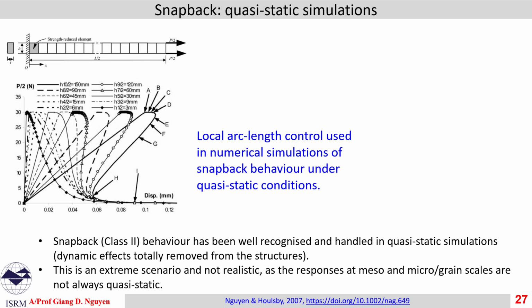So the first thing is this snapback. This is something well known in the community of concrete fracture. So I use here some example that we did a long time back. This is 1D tension of a bar, and you can see that if we plot the load against displacement, it can be obtained using different gauge lengths. So this is shorter, this is longer gauge length, and the longer the gauge length, that means the longer the specimen, the stronger the snapback we can see.